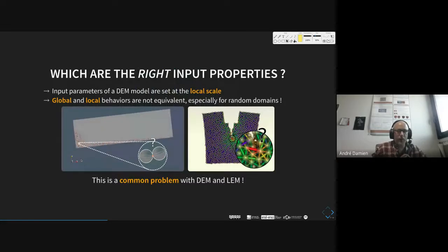But the main problem with this approach is what we have to put inside the local properties. The local properties for me are the properties of the discrete element and the bond between the discrete elements. So there is a problem. The input parameters of a DEM model are set at the local scale. So for example, you set the mechanical properties of this bond, and these mechanical properties are not known. In fact, we don't know what we have to put inside this bond. And this is the main problem, in fact, with the standard discrete element method for granular media.